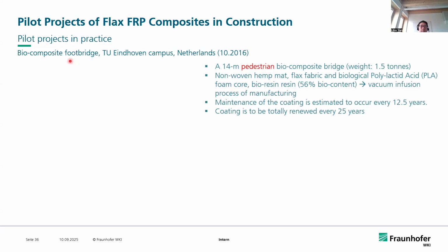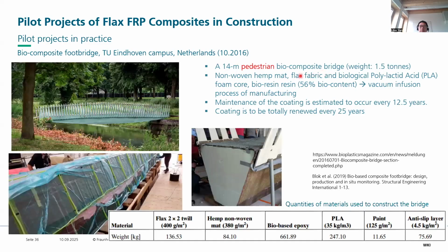The first pilot project is a 14-meter footbridge that was opened in the Netherlands in 2016. The composite bridge has a weight of 1.5 tons, which is very lightweight, and is made of non-woven hemp and flax mat fabrics and a PLA foam core, as you can see here. The mat fabrics and the PLA foam are bonded by the bio-resin using the vacuum infusion process. In this table, you can see the different materials used for this bridge. This is the first large-scale demonstration of biocomposites in infrastructure application.